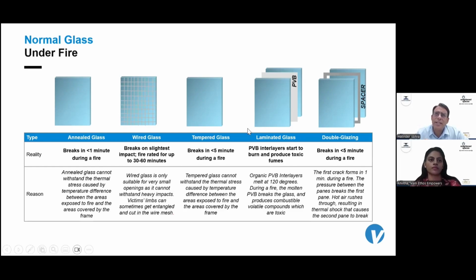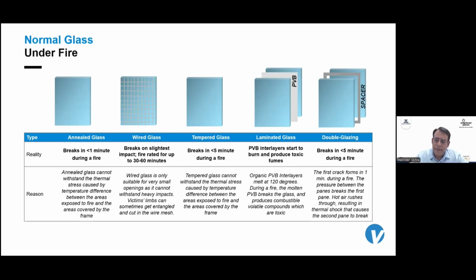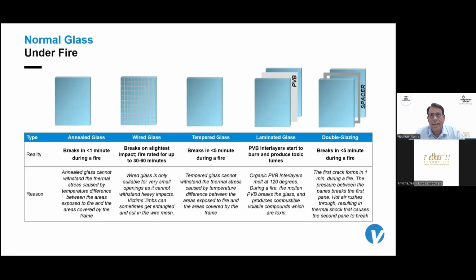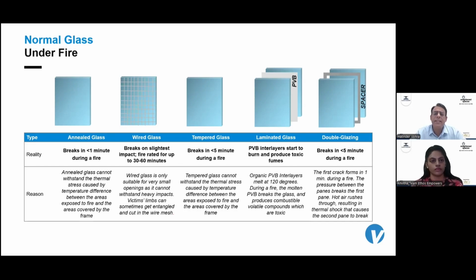This is because these products, due to delta T, due to the temperature differential, the basic structure of these glasses is like that. They are not able to withstand that heat, and they break. Unlike the fire rated glasses, they can attain higher temperatures, and they don't break till the time frame it is being tested. Let's say it is tested for 1 hour or 2 hours, it will withstand fire or that heat for 1 hour or 2 hours.